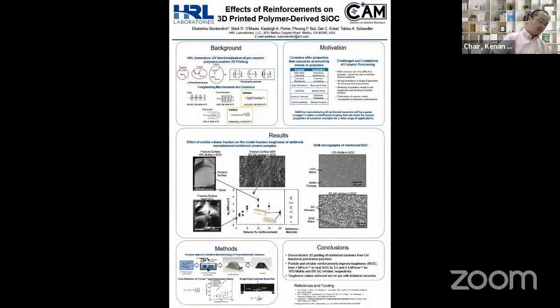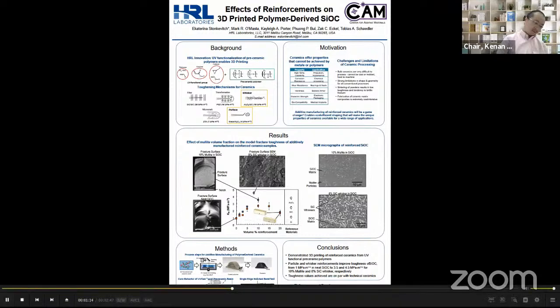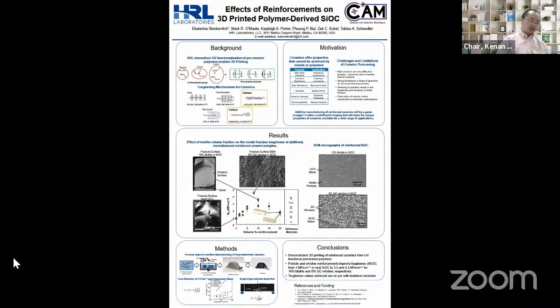In order to increase the toughness of our 3D printed ceramics, we can employ toughening mechanisms. The use of secondary phase reinforcements is a well-studied mechanism to increase the fracture toughness of ceramics. The two mechanisms that we're studying are particle reinforcement and whisker reinforcements. To quantify toughening of our ceramic, we used single-edge notched bend tests.